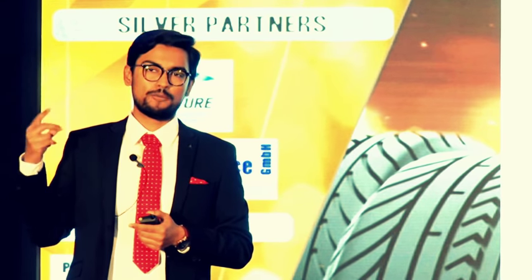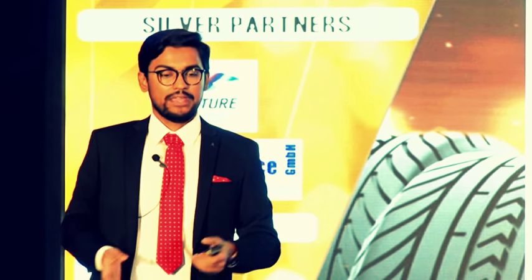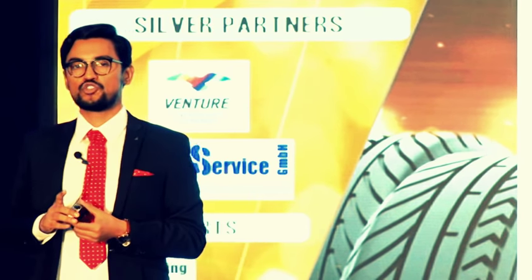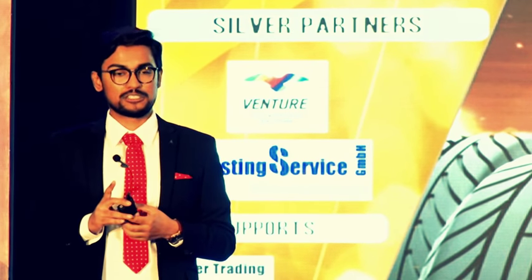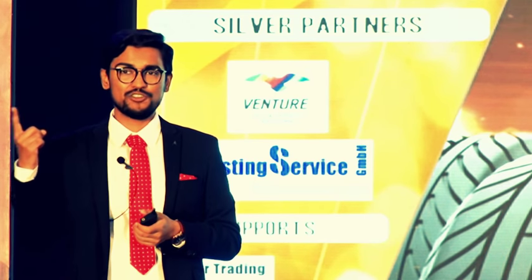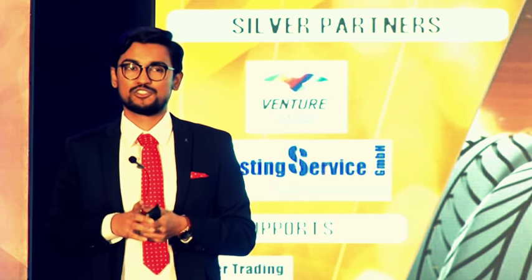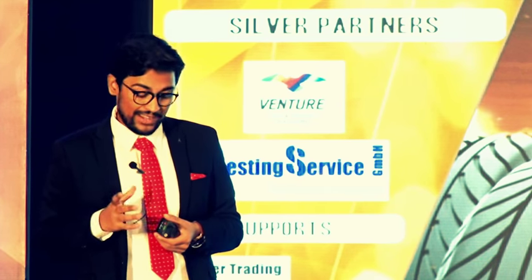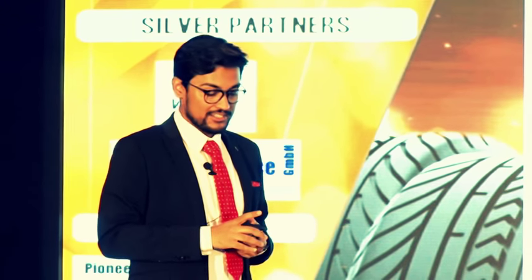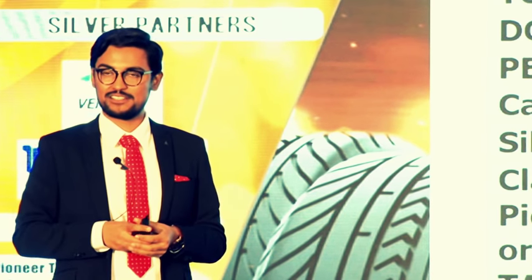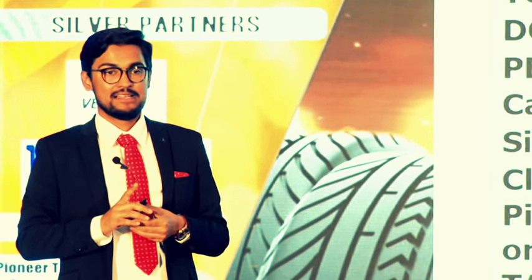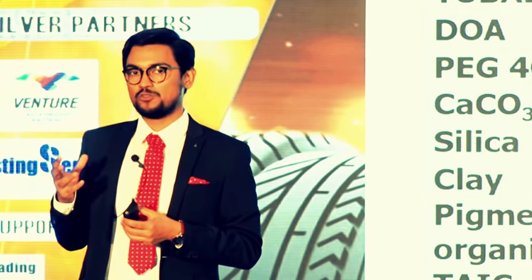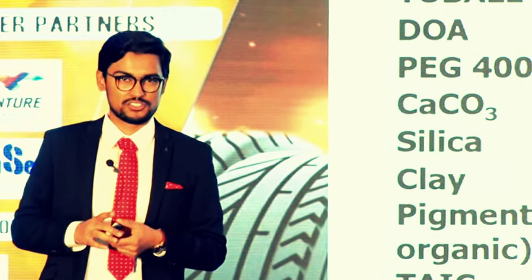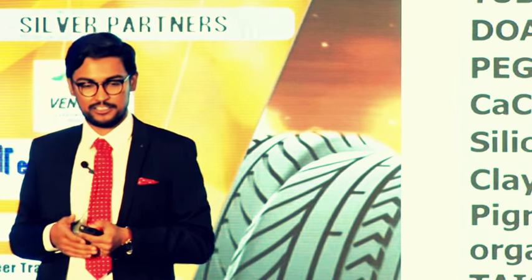There was one more objective of using carbon nanotube in these compounds, that was to bring about color. We wanted to explore the possibility of bringing in conductivity with color by using single-walled carbon nanotube. Why that? Because right now, there is no such combination possible. If you want a conductive compound, you would have to put in carbon black, which would essentially make the whole compound black. Colored rubber compounds are very, very interesting for some applications like solid tires. And then there are other possibilities also.